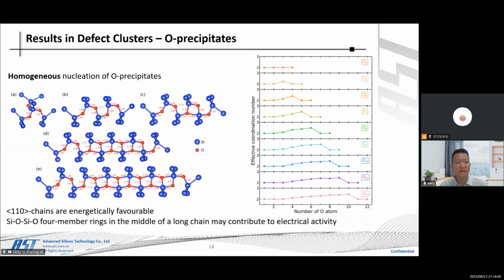Also, we studied clusters such as oxygen precipitates. There are two different kinds of oxygen precipitates. One of them is homogeneous nucleation of oxygen precipitates based on <110>-chains. Chains along the <110> orientation are energetically favorable. The silicon-oxygen four-member rings in the middle of a long chain may contribute to electrical activities, as shown in the figures.